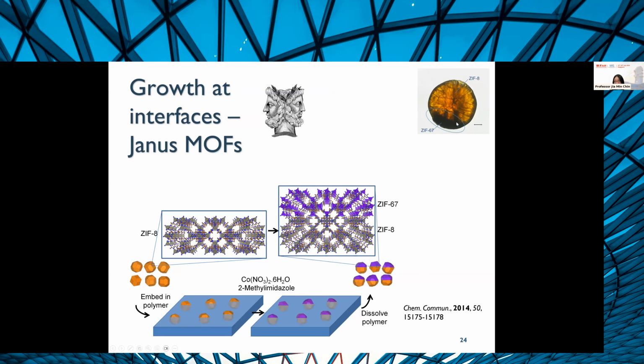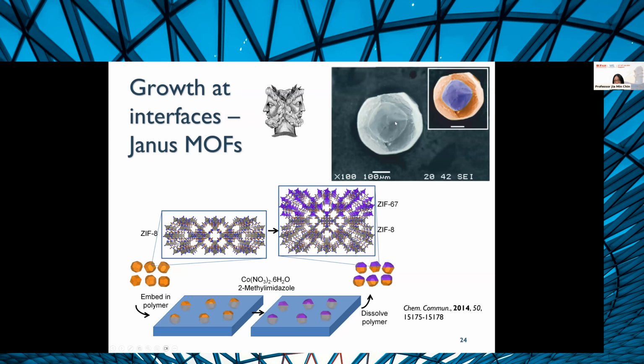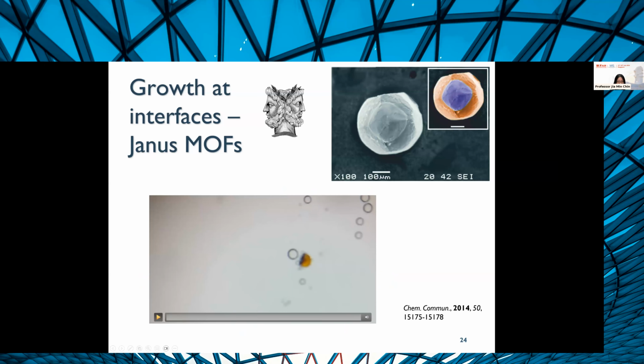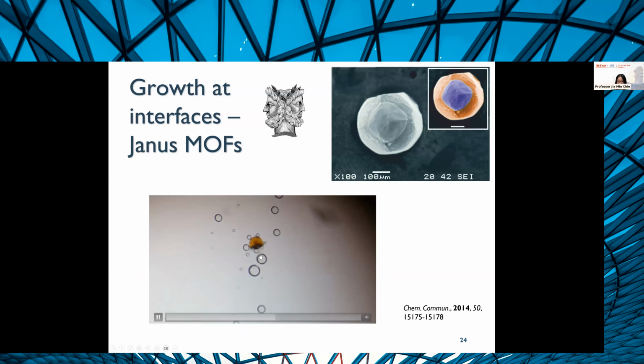We found that, indeed, we could grow these Janus particles or two-phase particles where you have ZIF-8 and then a little ZIF-67 cap. This is a false color SEM image where you have the ZIF-8 and then the little ZIF-67 cap here. And this is a little video showing what's happening. The ZIF-67 starts to break down H2O2 and you have bubble evolution. This video was taken with an iPhone by one of my high school students who was working on this. It was a really fun foray into this chemistry, again using interfaces.